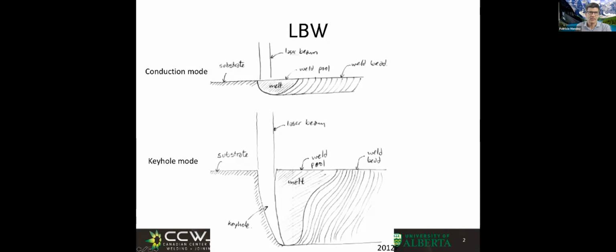In some aspects, it has some similarity with welding with 6010, but the physical mechanism is completely different. In 6010 it is the force of the arc that is drilling a hole. 6010 is stick welding. And in this case, what is drilling the hole is the evaporation of the metal, and we're essentially vaporizing the metal and causing a hole. And of course, the heat also creates a melt and the weld pool behind.